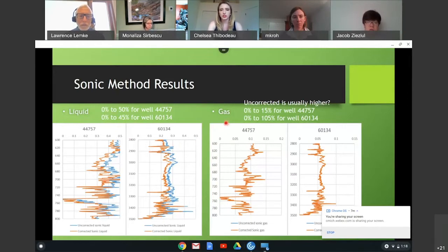What's really interesting in the gas scenario, like I mentioned, the uncorrected porosity curve tends to be higher than the corrected one, but for some reason in the gas, the uncorrected porosity values were below 0, so we had to omit them. But you're still getting pretty high porosity values, and that should not be 105%, that should be 10%. But you're getting higher porosity values with the sonic method.